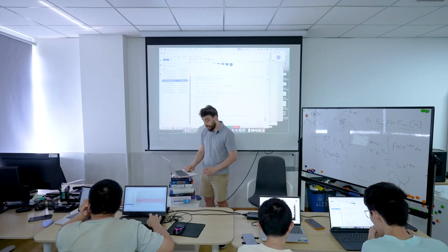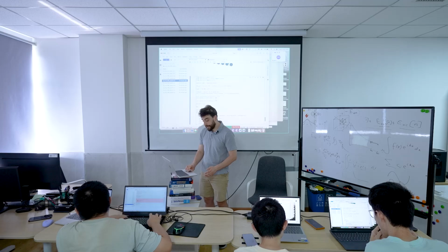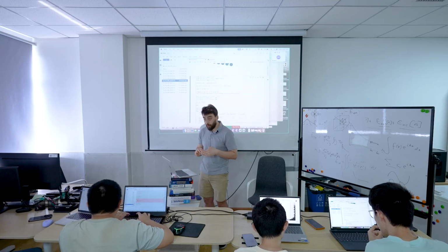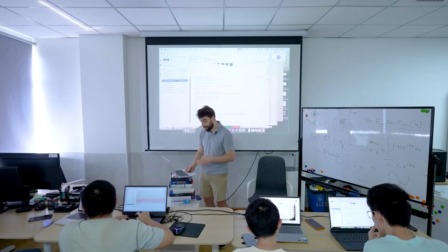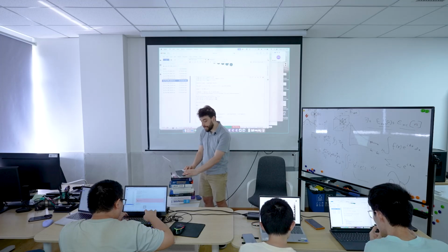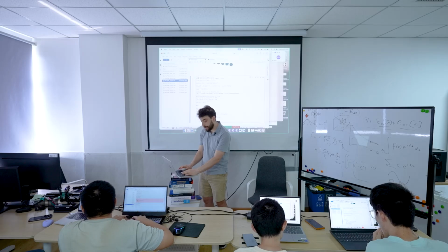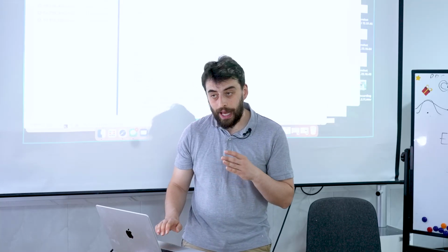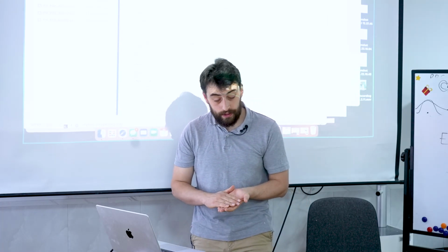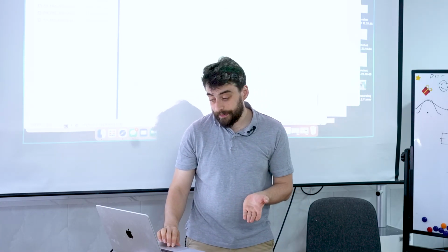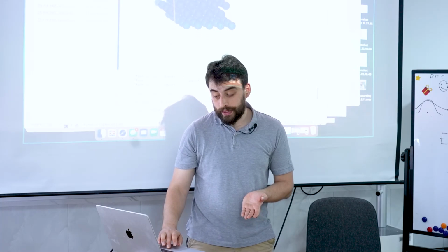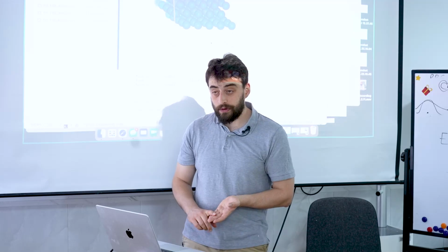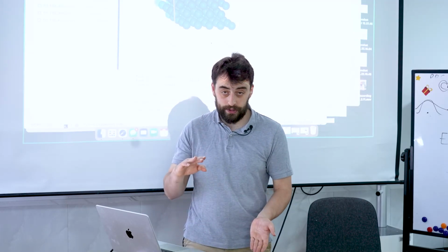For PD surf, I'm doing a CASTEP calculation with a cutoff energy of 600, and we said that we were going to do a 4 by 4 by 4 Brillouin zone sampling. So I'm going to say that my K-point grid is 4 by 4 by 4. However, because we're doing a surface, we can see that in the Z direction we have no symmetry. We've broken all symmetry.